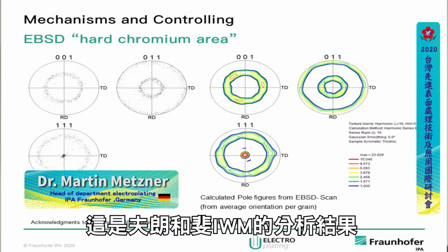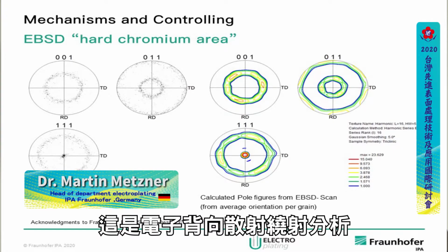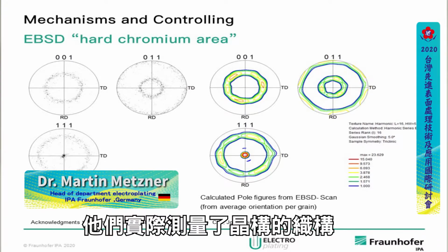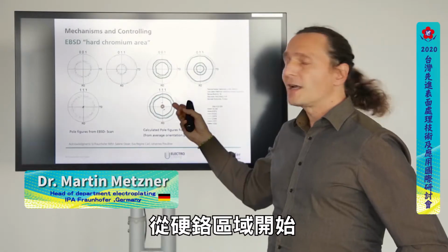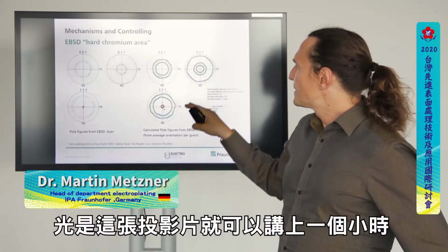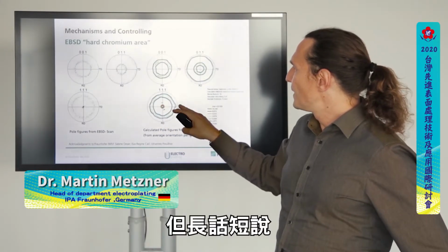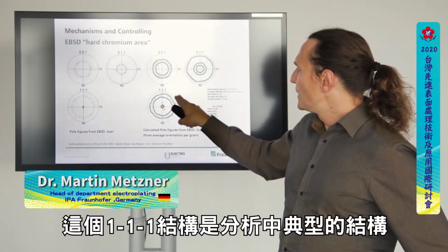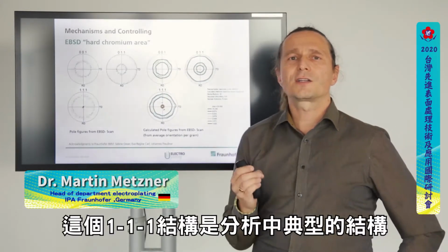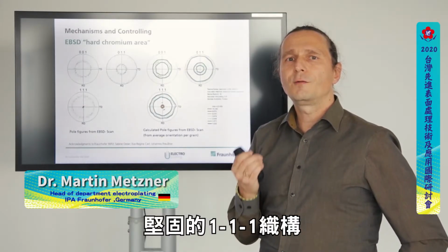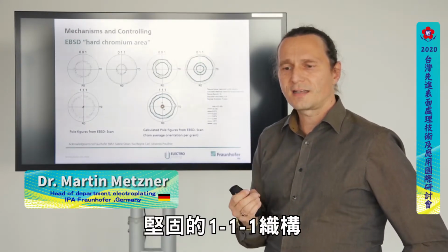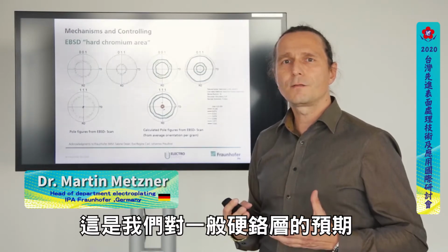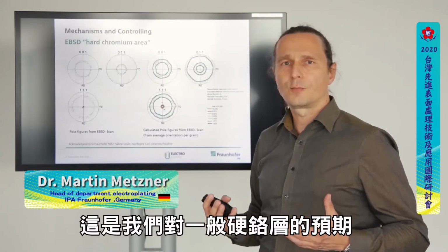And the analysis, you see this here from Fraunhofer IWM. This is electron backscatter diffraction analysis. So in fact they measure the texture of the crystalline structure from the hard chromium area. Only on this slide you could talk for 1 hour, but to make it short, this structure here, 111, is the typical structure in this analysis for a very, very strong 111 texture. So just what we were waiting for from a normal hard chromium layer.